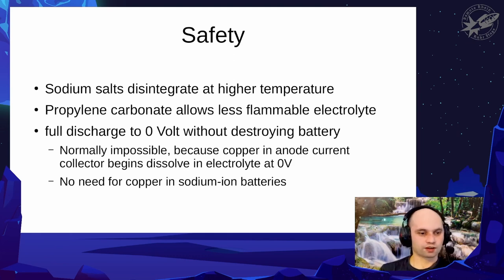One of the other advantages is that you can use propylene carbonate, which is liquid at low temperatures. In lithium-ion batteries, you have to use ethylene carbonate, which has a much higher melting point and only gets liquid at around 30 degrees. So on a very warm summer day it would be liquid, otherwise it's solid. And you need to mix it with other components that are very volatile, that turn into gas very easily and are very flammable. That's one of the main reasons why lithium-ion batteries can turn into fireballs very quickly. And you don't need those additives here to reduce the melting point, because the melting point's already very low. So that's why the flammability is not quite so bad.